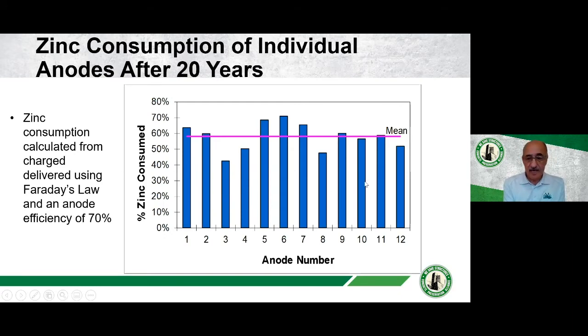This is all the anodes, mass loss by calculation using the efficiency of 70%. And we can see that on average we still have about 40% of the zinc remaining.